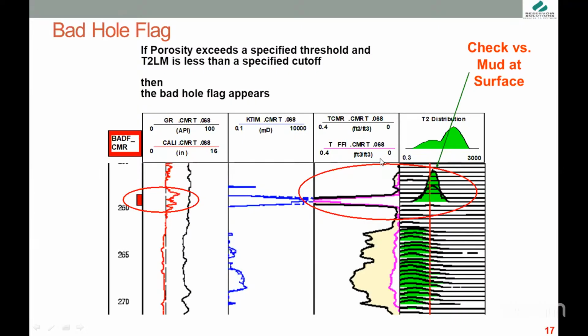Hello, this is in the case of a reservoir with poor petrophysical characteristics. When we run NMR, it gives us good permeability, but when we run a formation pressure test, we found that it is tight. In some cases, usually a reservoir with poor petrophysics and low petrophysical characterization. This is a good question, by the way, by Mr. Abdu. When we run NMR, it gives us good permeability, but when we run formation pressure, I think this reservoir is carbonate, Mr. Abdu, right?